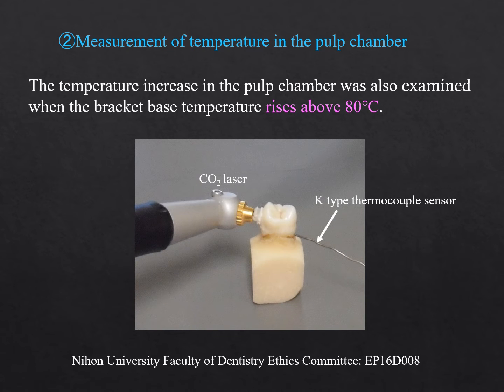A ceramic bracket was bonded to the buccal surface of a human premolar, which was removed for orthodontic treatment, using light-cured adhesive, and a hole was opened from the cemento-enamel junction on the lingual side. A K-type thermocouple sensor was positioned on the inner wall of the pulp chamber corresponding to the surface where the bracket was bonded. The measurement of the temperature in the pulp chamber was performed at a room temperature of 23 ±1 degrees.